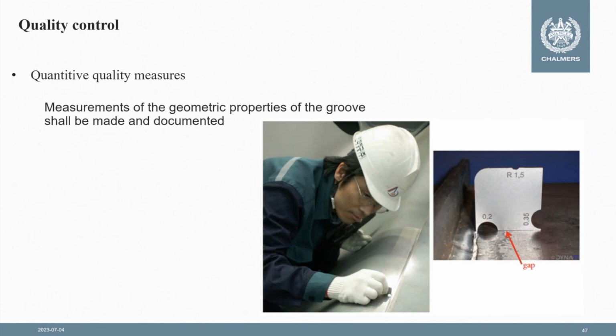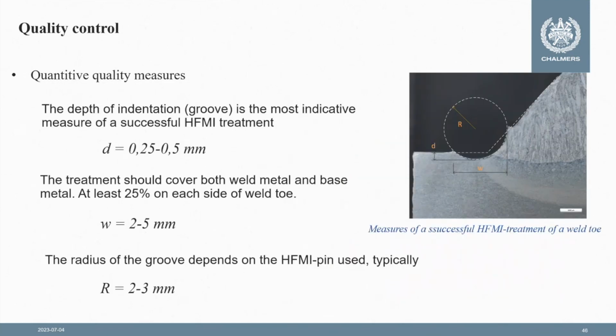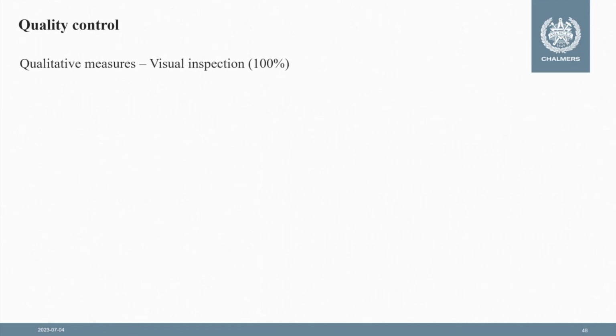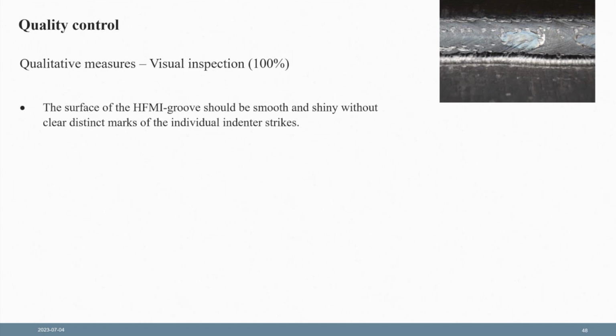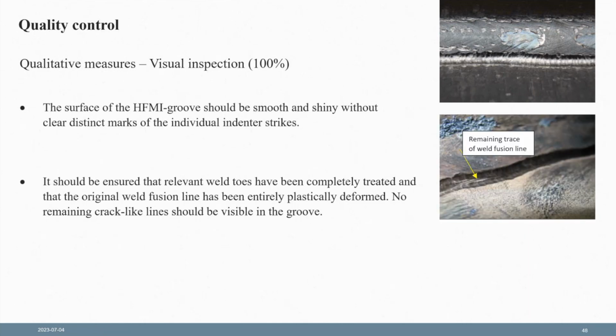There are different ways of measuring the quality. What you see here is a very simple way of using these gauges, but in some cases, laser scanners have been used to document that. The measurement of the quality should be performed in order to make sure that these limits, particularly the depth of the indentation, are correct. Visual inspection is important. It should cover 100% of the area which is treated. The surface of the HFMI groove should be smooth and shiny and without clear, distinct marks from the individual indenter strikes. It should be clear that no remaining traces of the weld fusion line are there.